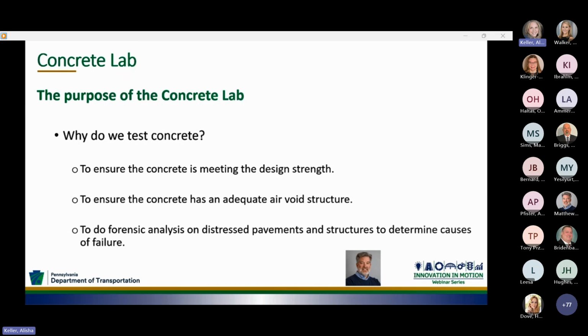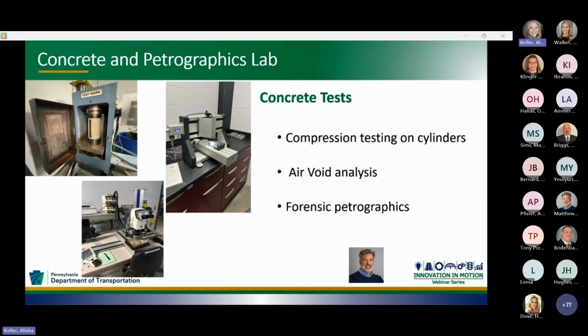Another essential function of the concrete lab is to perform forensic analysis on distressed pavements and structures and determine the causes of failure. The concrete lab is also responsible for doing concrete mixes and molding concrete prisms for our evaluation of an aggregate's potential to have adverse alkali silica reaction. Here's a look at some of the specific testing that is done in the concrete lab. Concrete compression tests measure the maximum load-bearing capacity of a concrete sample broken at 28 days. The 28-day break determines if the mix design meets strength to ensure structural integrity.